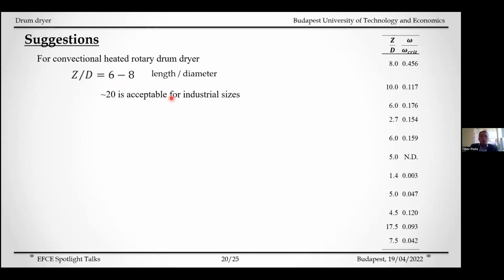The rotational speed doesn't always show the mixing behavior for rotary drum dryers. It depends even more on the diameter of the drum. Furthermore, it's advisable to compare the rotational speed to a limit at which the material hasn't yet started rotating with the drum, because centrifugation would occur. The following equation can calculate this critical angular velocity value. The ratio of the actual angular velocity and the critical angular velocity can be determined, which is about 0.1.